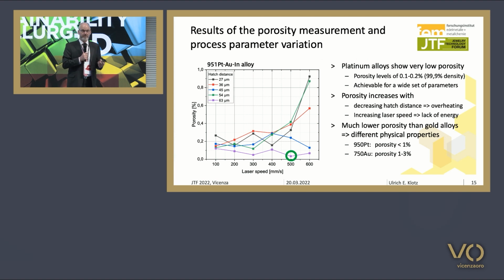We've changed the laser speed as a function and measured the porosity, and we also changed the so-called hatch distance. The hatch distance is the distance between two laser tracks. The laser is going forth and back to scan an area, and the distance is called hatch distance.